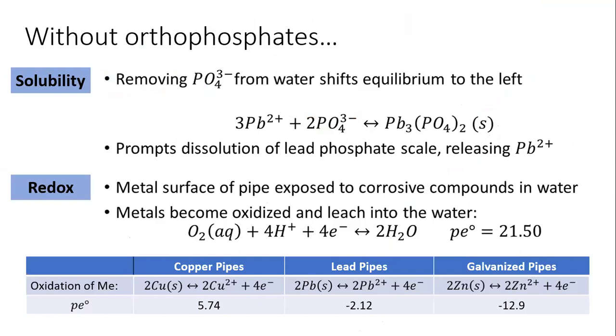Because Flint City stopped using orthophosphate as a corrosion inhibitor, the lead phosphate scale started to dissolve, releasing lead ions into the water. Also, the metal surface of the pipe was exposed to oxidation agents in water, such as dissolved oxygen. The metal was oxidized and leached into the water.